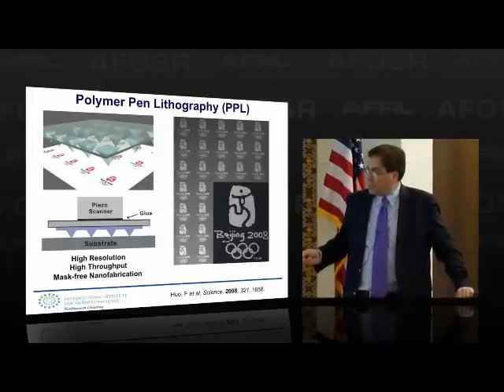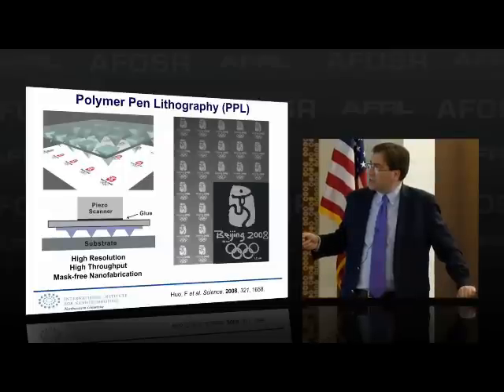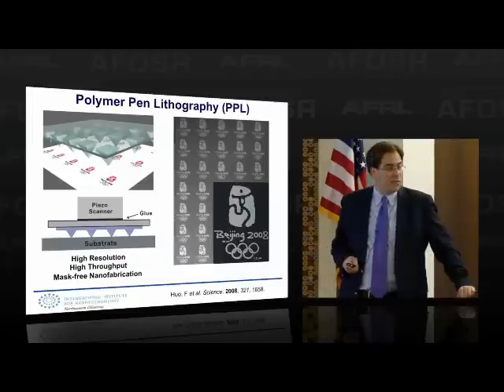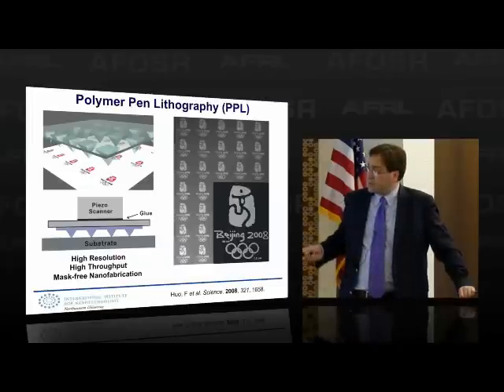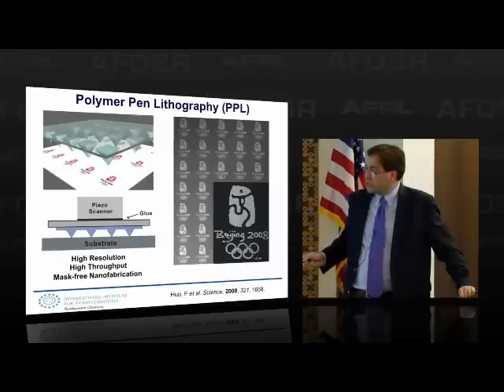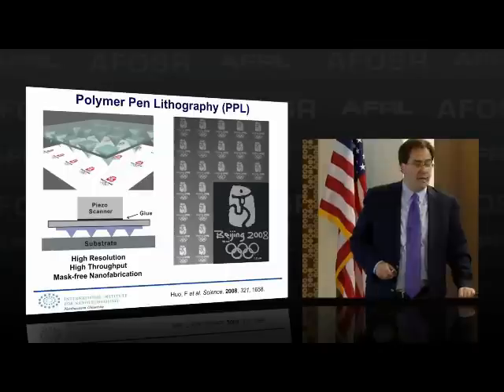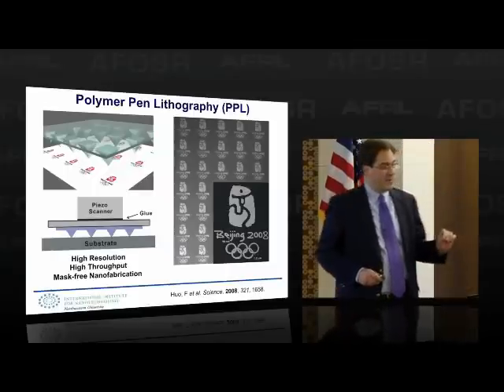But what struck me immediately was that these are large features. These are micron scale features. And in fact, the dots used to make the runner were 600 nanometer dots. And this is, of course, the Beijing Olympic logo. In the Beijing 2008, with the 5 rings, in this case, were made at 90 nanometer resolution.